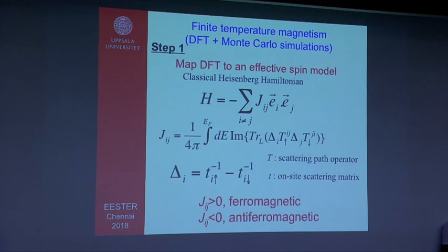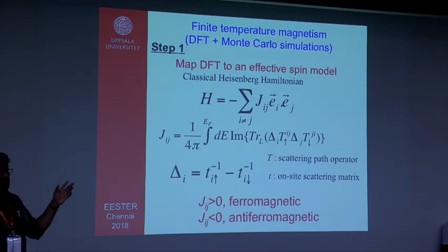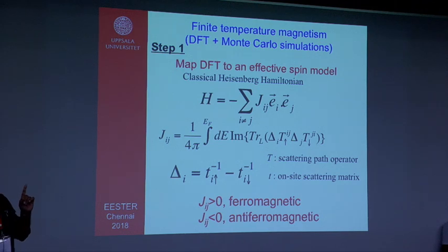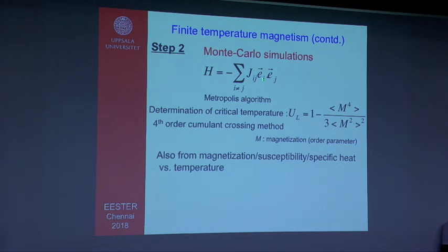Typically these Jijs are calculated as a function of distance, because in a solid, two atomic sites can be placed at different distances, and as a function of distance you can calculate these interatomic exchange interactions. Once you have that, in the next step you do a Monte Carlo simulation. You take a Heisenberg model once again, and for this Monte Carlo simulation you have these Jijs calculated from density functional theory, material specific parameters. You don't have to do anything else. Then you do the Monte Carlo simulation, some of you have already done this with the standard Metropolis algorithm, and then you look into certain thermodynamic properties, basically the phase transition and others.